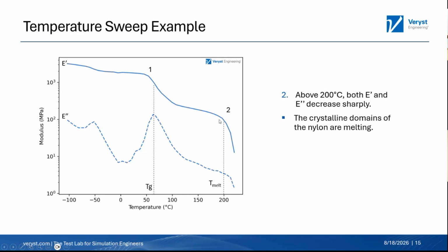At point number 2, this is the melting point for that nylon. So as I said, nylon is semi-crystalline. And so this is where we're actually measuring the onset of melting for these materials. And so we can use the DMA to not just measure these characteristic temperatures, the melting point and the glass transition temperature, but just as an engineering exercise, it's very useful to think about how the stiffness of your material changes with temperature, to help assess what are the risks of various failure modes or excess deformations across different temperatures, versus in shipping versus storage and things like that.